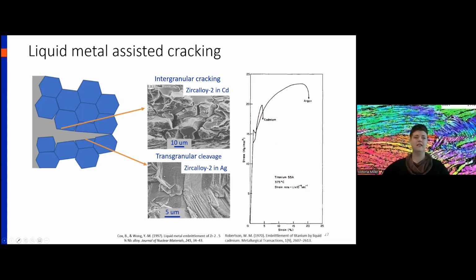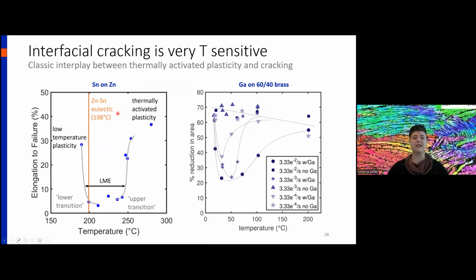This particular liquid metal embrittlement mechanism is very temperature sensitive. So again, this is our tin on zinc plot. Embrittlement only occurs in this relatively narrow 50°C window. And again, this is gallium on 60-40 brass. Depending on your strain rate, your embrittlement may only occur in a 30-degree window or in a 100-degree window. So it's very sensitive to temperature. You get multiple temperature transitions.